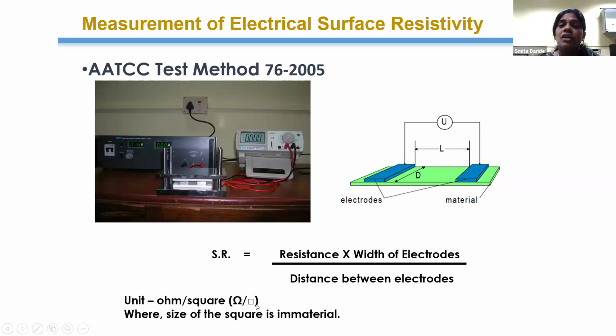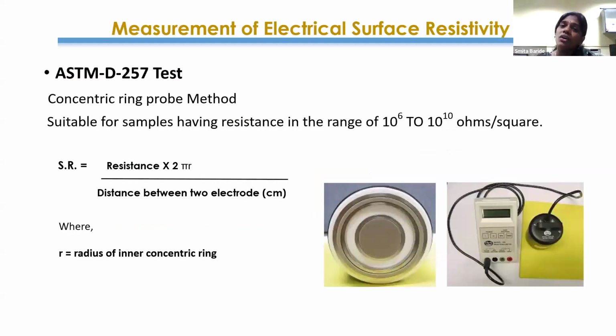For that kind of sample, the AATCC 76 test method is used. This setup we have fabricated as per this standard method. It includes a two-probe flat plate electrode system to measure the resistivity of the sample, and we are able to measure resistivity ranging from 10 to 10,000 ohms per square. But for anti-static clothing, which generally has resistivity more than 10 raised to 5, we need to use the ASTM D257 standard method, where we use the ring probe method to measure the resistivity. So these are two different techniques for resistivity measurement.